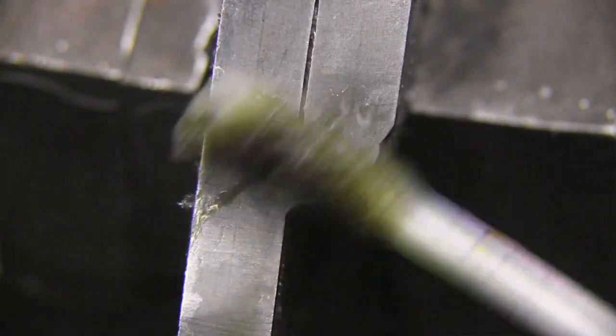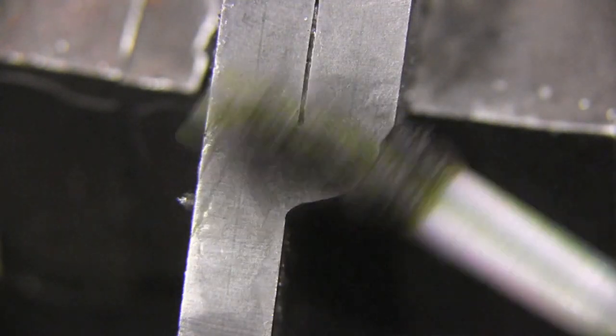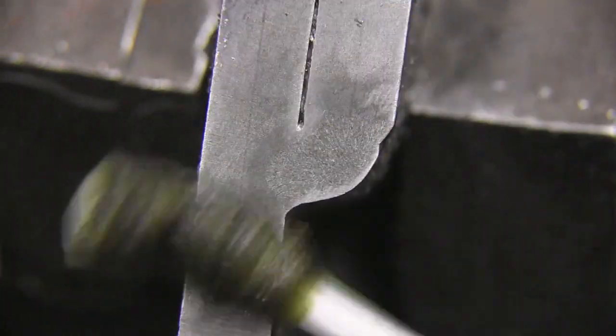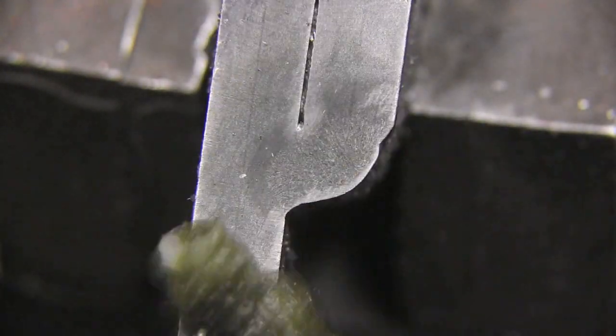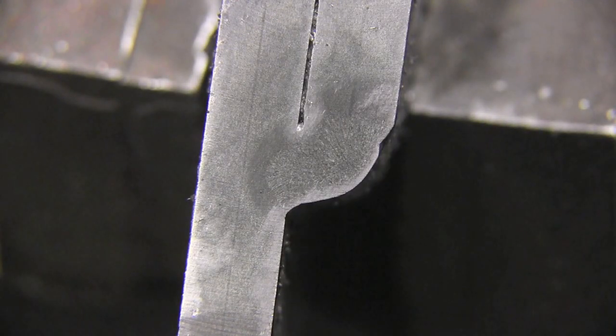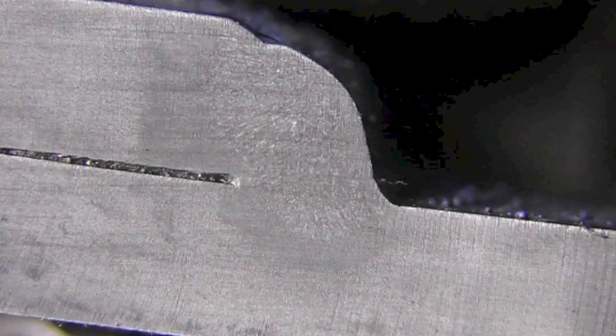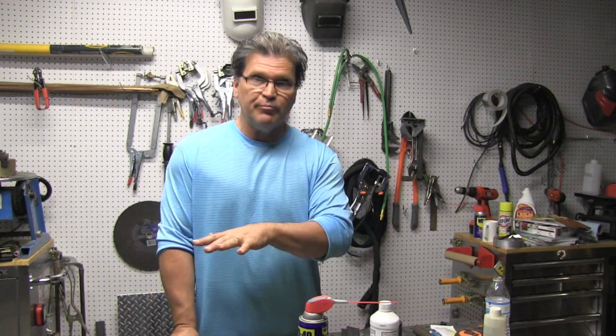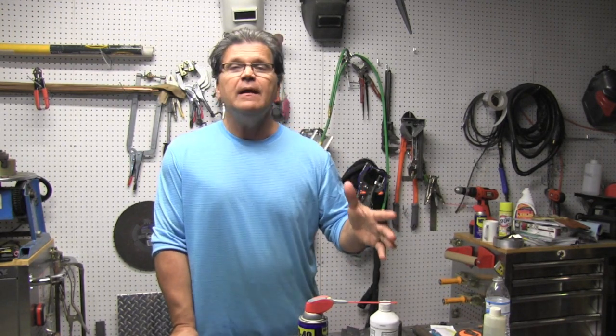Again, you can use Loctite naval jelly rust remover. It just takes longer to reveal that weld nugget. I just happen to have this stainless steel heat tint remover. And that's a good nugget. So cleaning or not cleaning, vertical up, big difference than vertical down. Mill scale can be different on different shapes. It's going to be different on plate than it is on box tubing, etc.